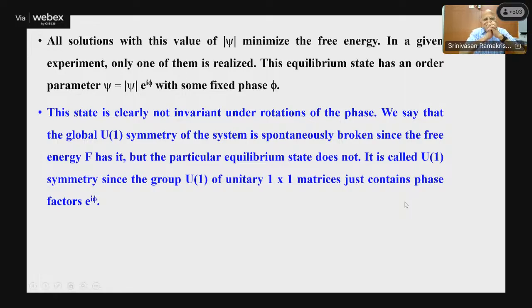What they were able to show is that all solutions with this value of psi minimize the free energy. In a given experiment, only one of them is realized. So the equilibrium state has an order parameter psi equal to mod psi e power i phi with some fixed phase. So what is happening in the superconductor? Which symmetry is lost? Earlier, phi in the e power i phi could assume all values, whereas in the superconducting state there is going to be only one fixed phi. So that is the symmetry which is not invariant under the rotation.